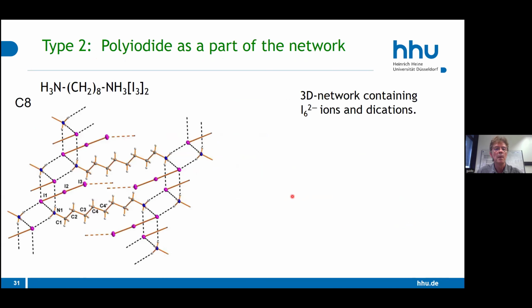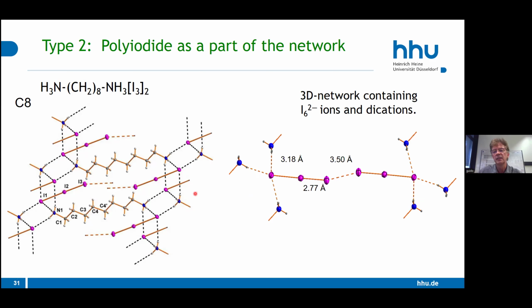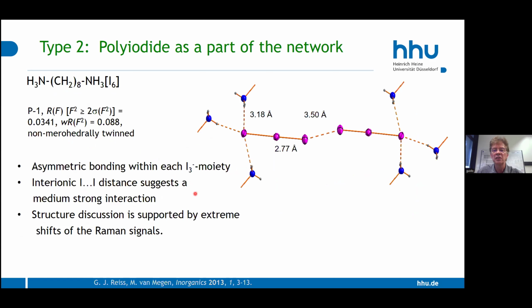A really interesting case we got from the C8 compound. Also here, you just follow my pictures. You have these squares that are connected to each other, and it's again connected to the next chain of squares. But in this case, we really got an interesting case because we had an I6 2- anion inside. And when we published it in those years, it was more or less not characterized. And also in this case, we had some discussions with reviewers if it's really an I6 2-, but we should go into detail.